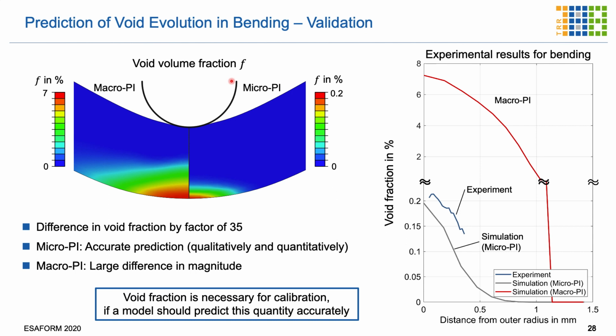So if we consider the bending process with a macro parameter identification method, which is the classical one, and with the micro one, you get completely different void fraction distributions. As you can see here, the factor difference is 35. Here is the distance from the outer radius, so we start at this point and go inside and measure the void fraction. If we use the macro parameter identification strategy, we get values, so please notice the coordinate system is cut at this point, so you have a jump here to values of 7%. If we measure them, we measure values of 0.2%.